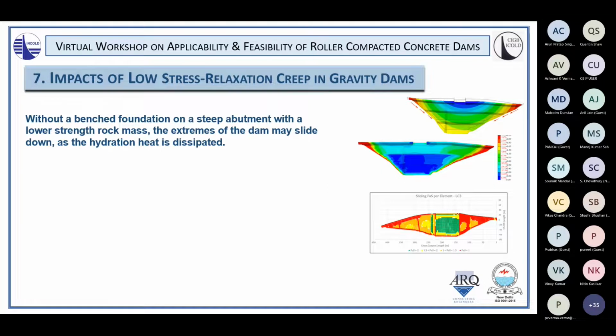Without a bench foundation on a steep abutment with a lower strength rock mass, the extremes of the dam may slide down as the hydration heat is dissipated. What would normally happen in a gravity dam is that each of the blocks would carry their own load vertically and they will shrink away from each other. But because of the thermal expansion that we have and the low stress relaxation creep, we actually create a situation where we lift our dam. So the top piece that we're putting on is sort of stretched over this lifted area. And as that lifted area cools and shrinks back down, it will pull the sides of the dam down the abutments. So those flanks of the dam must be designed to be stable on their own abutment.